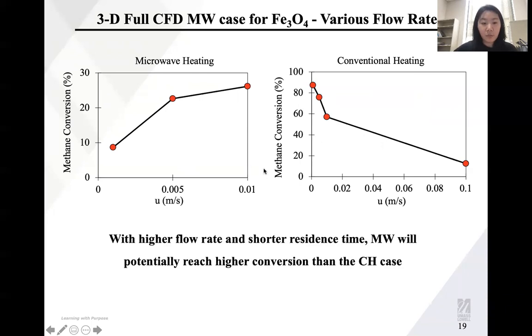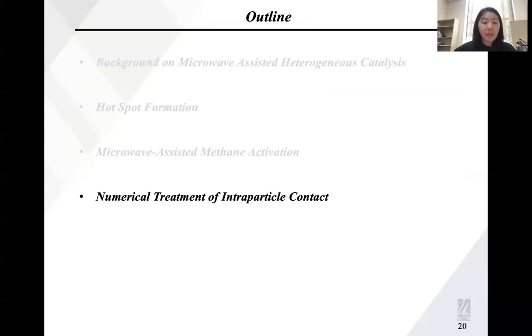So from this result, our preliminary conclusion is that with a higher flow rate and shorter residence time, the microwave heating can potentially reach higher conversion as compared to the conventional heating case. So this gives us a hint that when we design our microwave reactor, maybe we can have a shorter bed and have better energy efficiency as compared to the conventional heating. Then go to the last part.